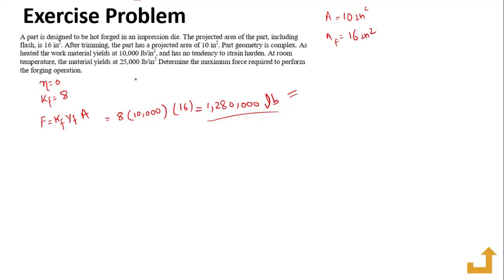This is because of the formation of flash in the forging operation. So flash, as we have seen, has certain advantages, in that it constricts the material within the die cavity, which helps us to fill the minor details in the cavity. But on the other hand, it increases the force required to perform the forging operation.